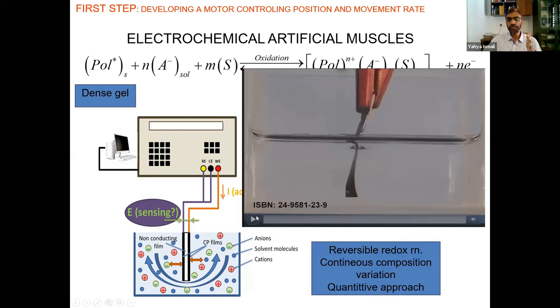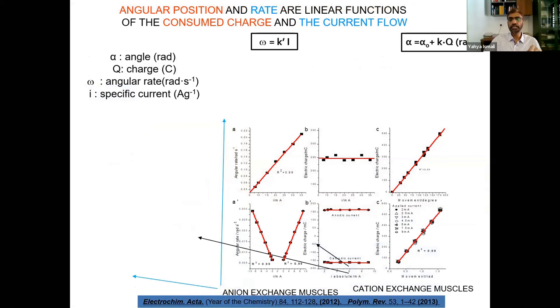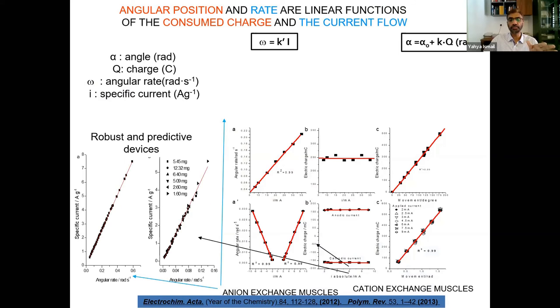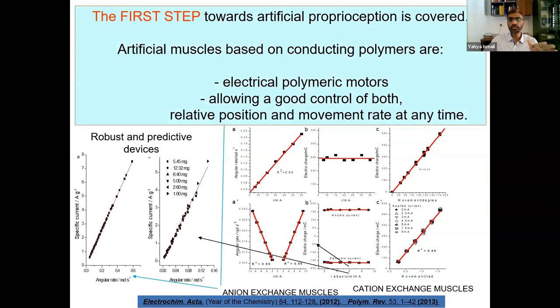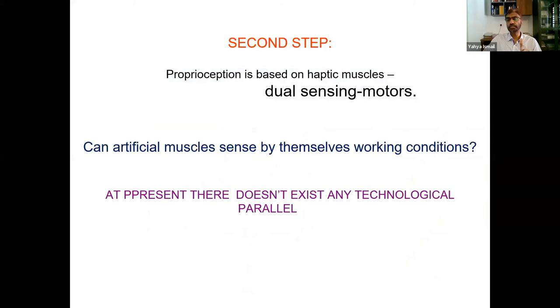This trilayer actuator has a double-side tape, and on both sides you have conducting polymer. During one cycle, one polymer film will act as a counter electrode, and the other will act as a working electrode. In the reverse cycle, the previous one will act as working, and the second one will act as counter electrode. Then we tried to understand the movement and position, the correct angle, and we got very good similarity. That means they can be used to control the position and movement rate.